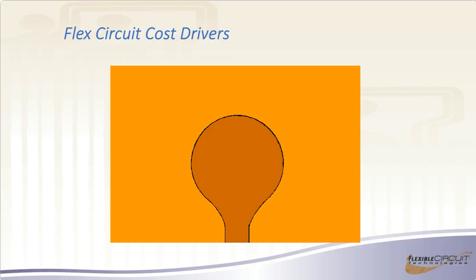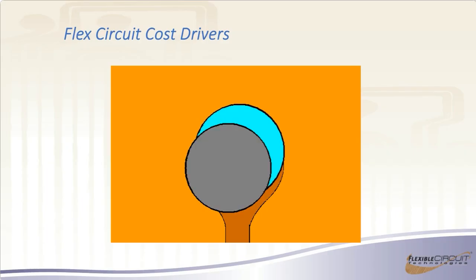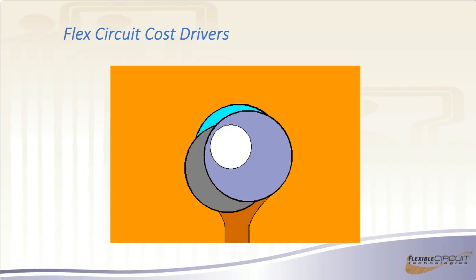And here's just an example. Let's say you have a 4-layer circuit. You have one pad, and now you have to take your next layer and stack it up. You have a little bit of misregistration. You do your next layer, and it's off a little bit, and your next layer. And now you have to drill a hole and make sure you hit all of those pads so you have annular ring on each layer. The fact that the materials are moving around, dimensionally unstable, can really cause a problem.